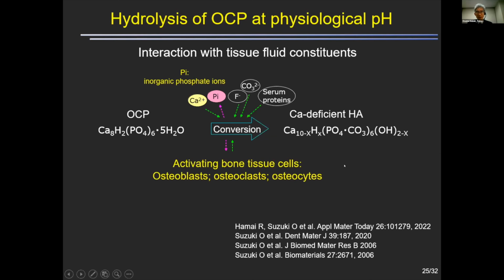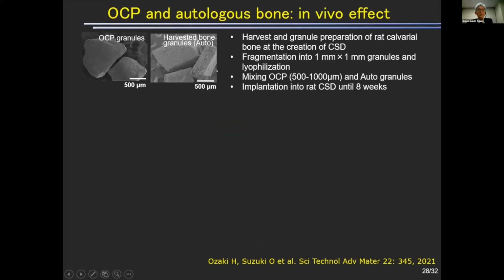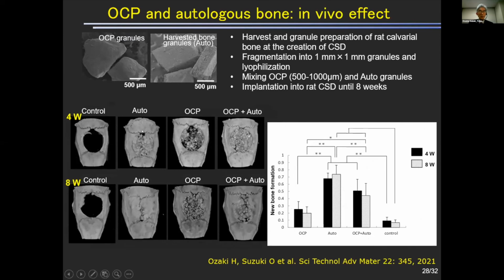So we pay attention to the effect of ionic dissolution products from OCP, to know the effect of OCP and why OCP has a higher osteoconductive property than the other calcium phosphate materials. We prepared autologous bone harvested from rat calvaria when creating CSD in the rat calvaria, and also prepared OCP granules having 500 to 1,000 micrometer diameter, mixed them, and then implanted them into the calvarial defect.